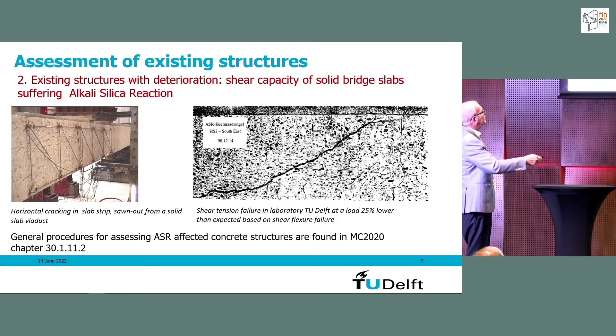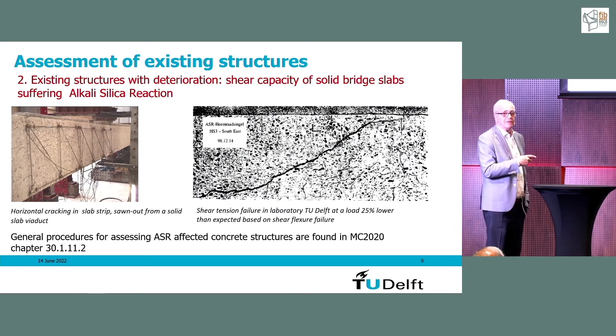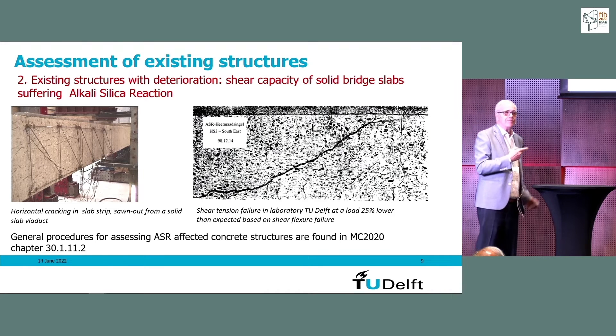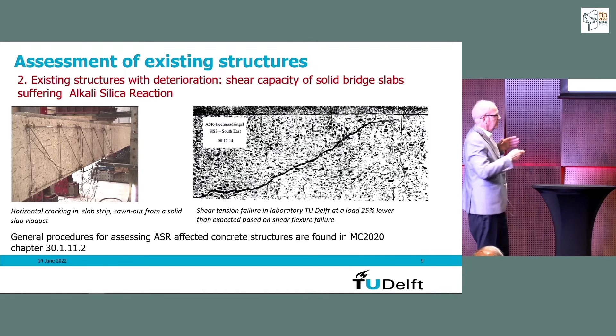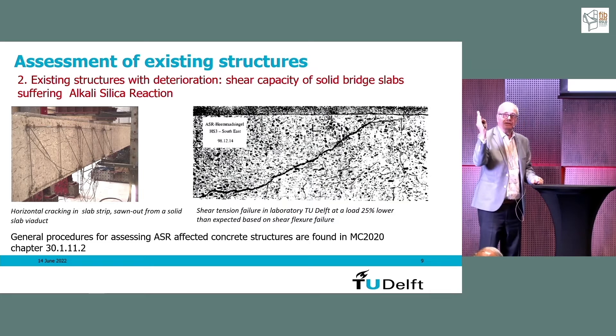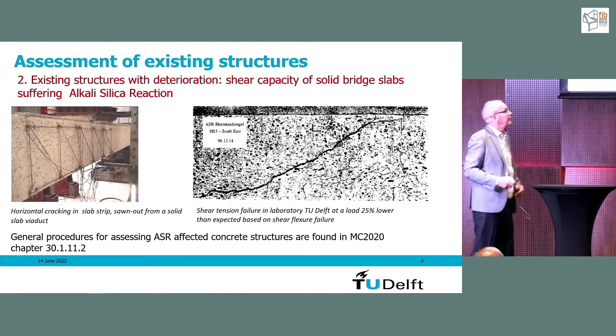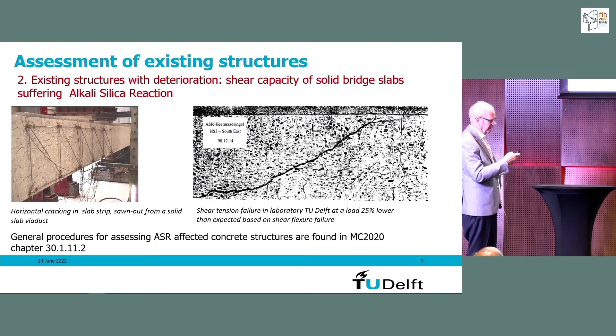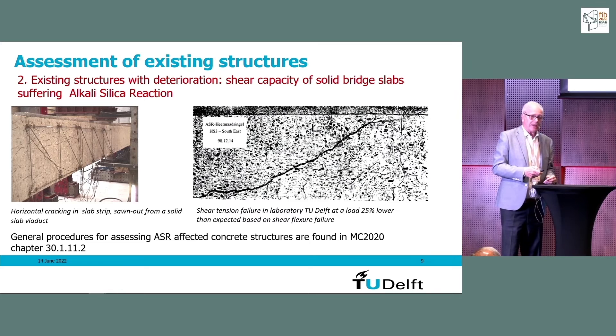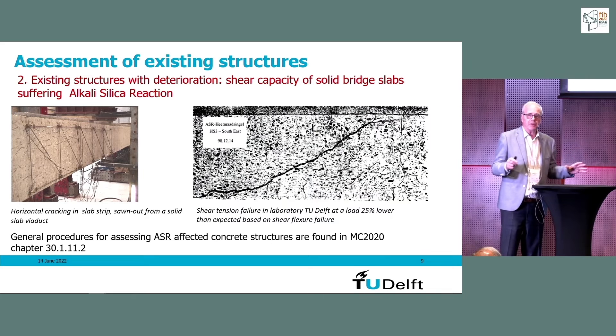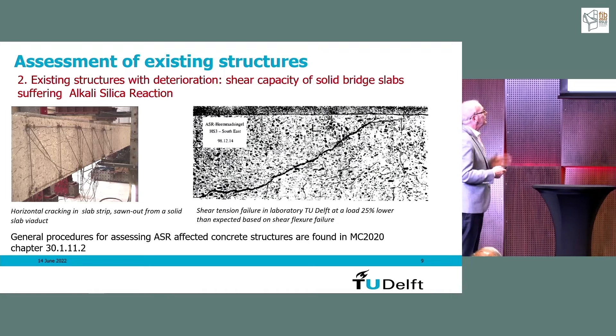This shear-tension failure was reproducible because in the vertical direction there is a strong reduction in concrete tensile strength due to the horizontal cracks, while in the other direction there is not. We have a distribution of tensile strength depending on inclination, and from this we could find a model that explains the behavior. When making an assessment, you must understand what can happen — relying on understanding of models rather than formulas alone is essential.